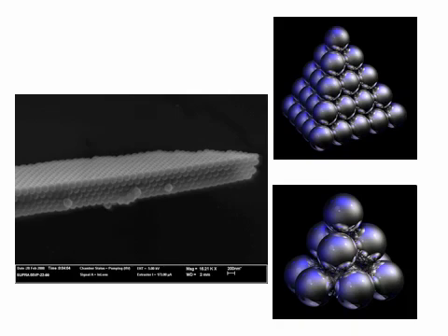Here is a pretty cool picture. This is an FCC colloidal crystal of spheres, about 150 nanometers in diameter, and you'll see they're beautifully ordered. In 2D at the top, if you count, you have 6 neighbors. And in 3D, how many neighbors do you have? 12. Yeah, 6 in plane, 3 on top, 3 at the bottom.